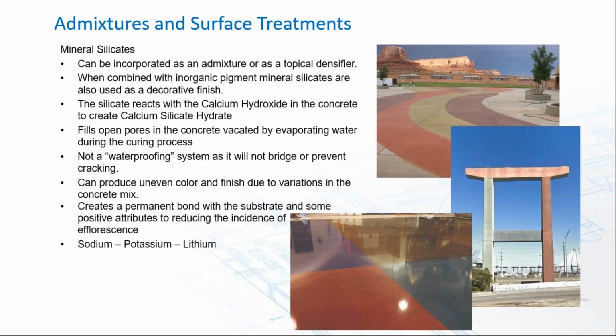Mineral silicates can be incorporated in an admixture as well, or as a topical densifier. When combined with inorganic pigments, these mineral silicates can also be used as a decorative finish. The silicate reacts with the calcium hydroxide in the concrete to create calcium silicate hydrate. This, much the same as the crystalline treatment we saw on the last slide, fills the open pores within the concrete vacated by the evaporating water. Again, not truly speaking a waterproofing system, as it will not bridge cracks or prevent cracking.